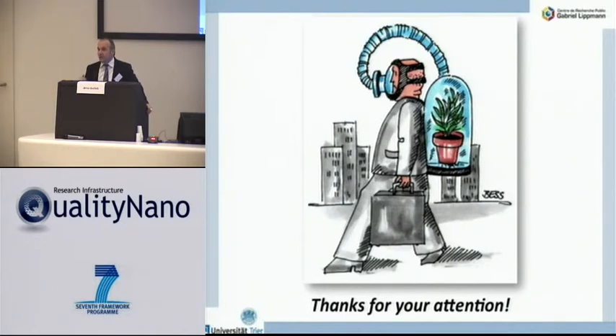What we plan to do, and I didn't show it because it goes beyond the scope of this talk, we have in-house an equipment called nanoSIMS. It's secondary ion mass spectrometry. We can expose the cells for whatever period of time, take the Transwell, and put it into an equipment that destroys the material but gives you a mapping for 5 isotopes. So you will see where you have carbon, this will show you where your cells are.